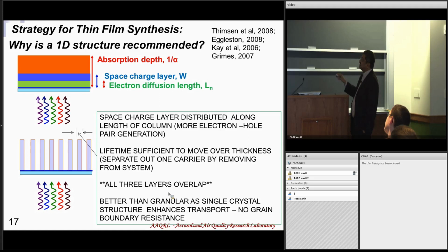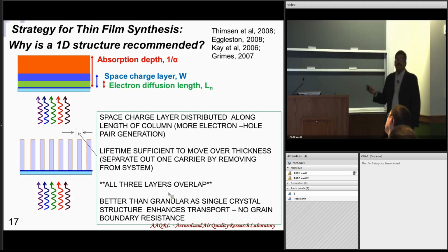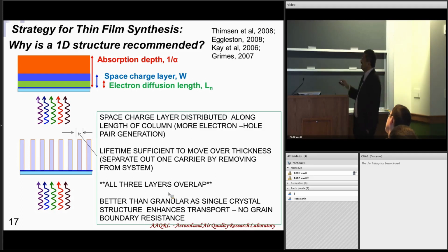Now how do I take this and make it more effective? This is why I'm justifying a one-dimensional morphology or a one-dimensional structure, and why it is recommended. The space charge layer could be distributed along this long column, and then I could have a significant region where the electron hole pairs are generated or separated, right? And then the lifetime is sufficient. This length is now sufficient to separate out the carrier by moving it out of this structure, right? So these three layers overlap. So a structure like this could be important.